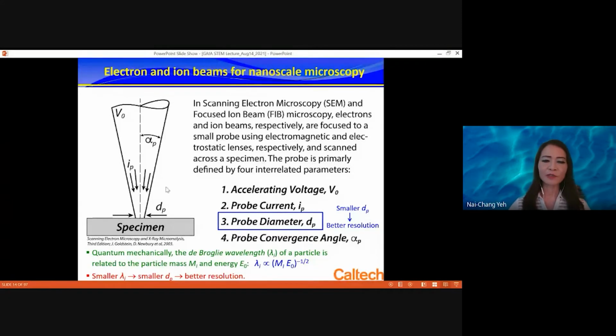Okay, so finally you have this probe. You have electrons or ions coming and focused onto this probe, and then this is your sample. The result will be sensitive to the voltage you apply, the current of the particles you have, the angle, how you focus, and the probe diameter. This probe diameter, you want it to be as small as possible so that you have better resolution. Quantum mechanically, you think about these massive particles. Photons have no mass, but particles have masses, and there's something called the de Broglie wavelength. That's completely a quantum mechanical concept.